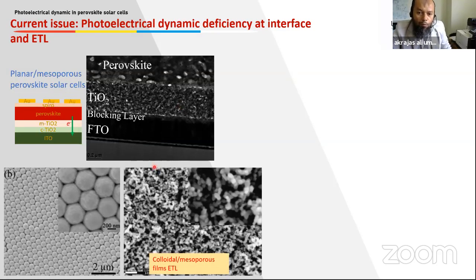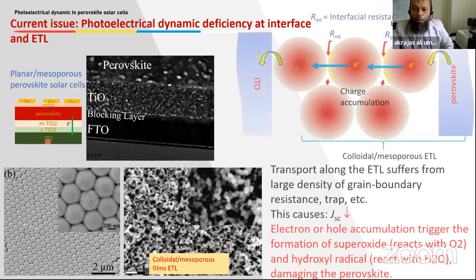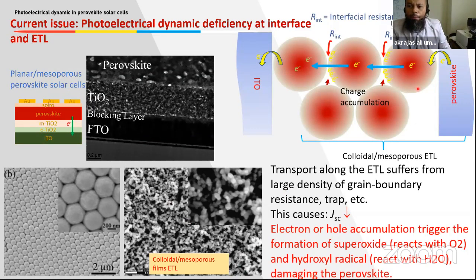If we look at the top view of this porous structure, we can imagine that it consists of large random pore structure and also connecting colloidal structure, which also produces large-scale interfacial grain boundary resistance, which also influences the dynamics of photogenerated carriers in this structure. So now when an electron is injected into the structure, it experiences the structure until it successfully reaches the ITO. So I describe the process with this model.